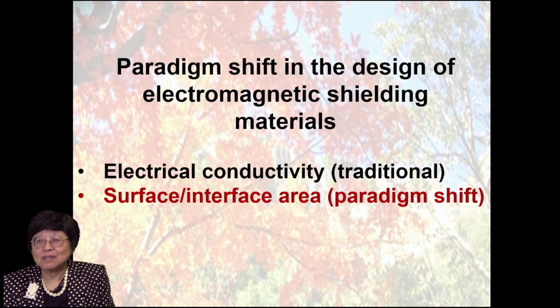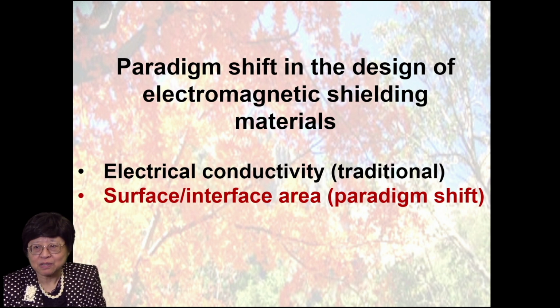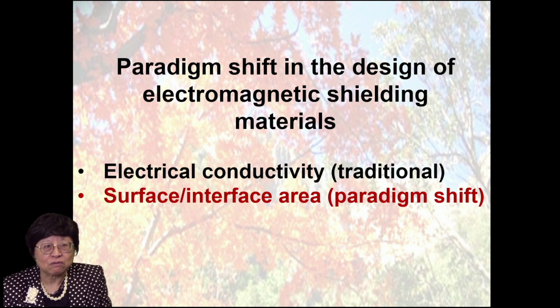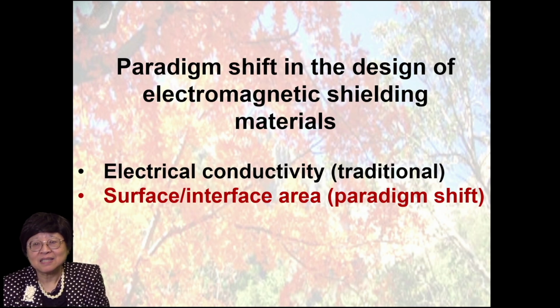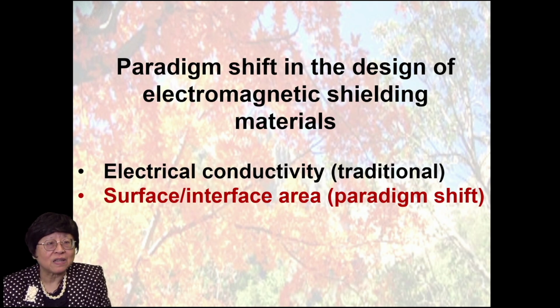So we brought about a paradigm shift in the design of EMI shielding materials. It used to be just electrical conductivity as the only criterion. But now we realize that there's a second criterion, that is the surface or interface area being high can help a lot.